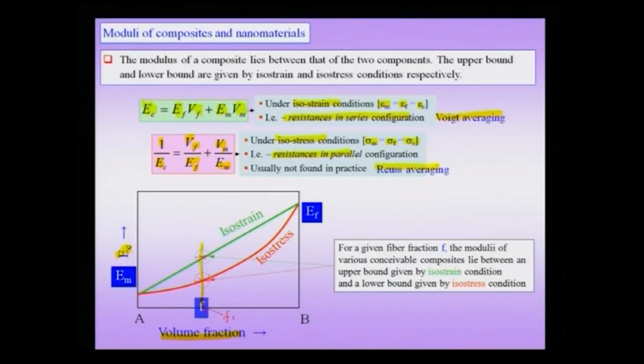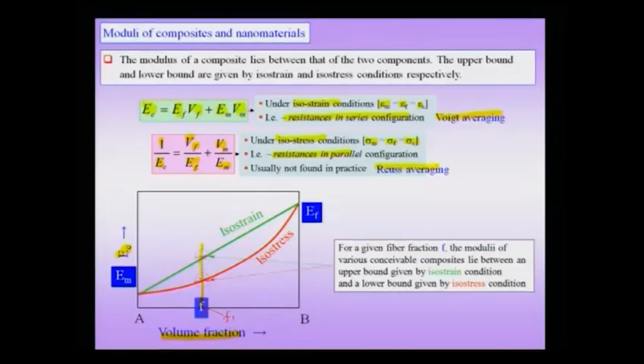And of course, in typical composites, you do not add up to 100% of the fiber. Usually, the fiber concentration is between about 5% and 25%. It is a smaller fraction as compared to the overall matrix. Of course, there are exceptions where we may go to higher volume fractions. Therefore, for a given fiber fraction f, the modulus of various conceivable composites lies between the upper bound given by the isostrain condition and a lower bound given by the isostress condition.